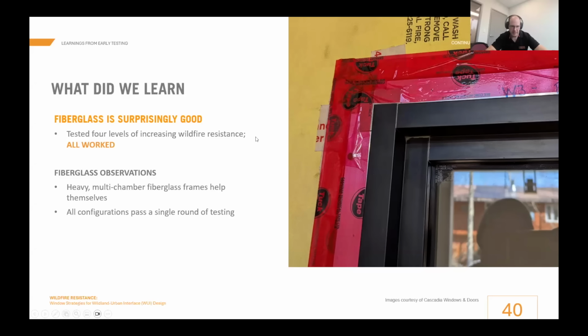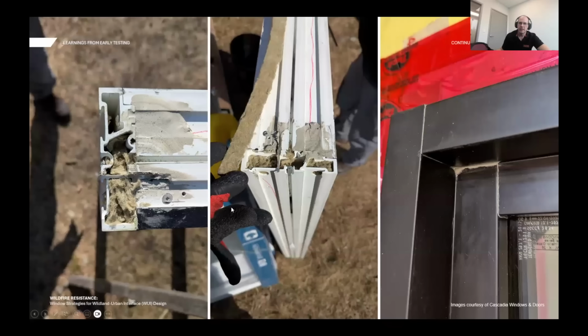What did we learn about frames? We learned that heavy multi-chambered fiberglass frames kind of help themselves. So even the fiberglass without any fire retardant passed and fared quite well. And so I've got some cutaway where after we did the test, we used a saw to chop through the fiberglass frame. So I'll show you those photos. This is before the test. So as you can see, before the test, we have these multiple chambers. They're normally foam filled, but we put about 2 inches worth of mineral wool just in the more robust version of these in the test.